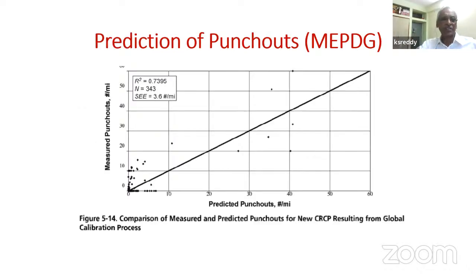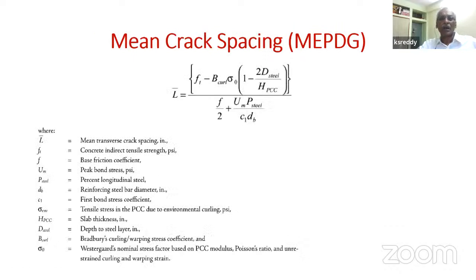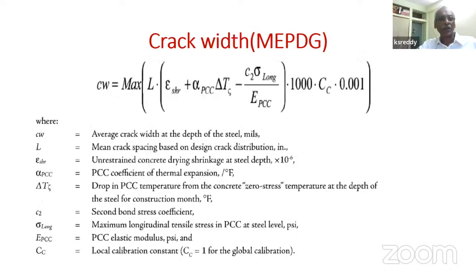They're trying to convince us that their estimated punch outs and measured punch outs match reasonably. This is an estimation of what is going to be the average crack spacing for a continuously reinforced concrete pavement with a given thickness, given grade of concrete, and given reinforcement. You can estimate that if you have all these inputs available. You can also estimate the crack width, again if you have all the inputs available, including temperature drop, coefficient of thermal expansion, and so on. These are the parameters that we're trying to control: crack width and crack spacing.